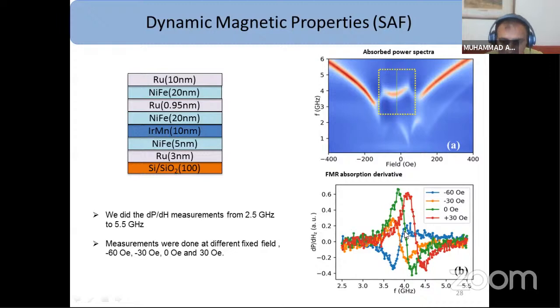This represents the resonance frequency. We can measure the resonance frequency from here. The measurements of dP by dH are done in the perpendicular direction, that is the z direction, because in the parallel direction it is very difficult to find the derivative in this unsaturated state.